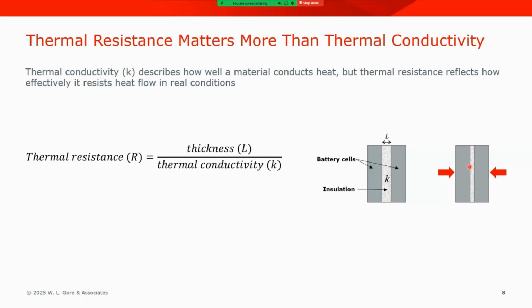Now imagine that you apply some compression. And so if the thermal barrier layer is compressible, then that value of L is going to decrease, which means that upon applying compression, the K value will often remain constant. However, the R value, the thermal resistance, will decrease in conjunction with the decrease in thickness.